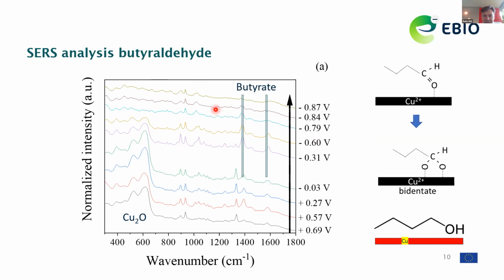And interestingly, when we start from butyraldehyde, we see a couple of bands appearing at intermediate potentials, which we can assign to the adsorption of the butyraldehyde in the form of an oxidized butyrate structure that you see depicted over here. So it's a kind of acidic C double bond O that is actually bound to the surface, and the double bond is divided over the two oxygens, and in that way it nicely bounds to the surface. And then if we remove the oxygen from the surface of the copper, we simultaneously reduce this butyrate structure, and then we start to see the product, which is in this case butyl alcohol. And then you see indeed these features disappear when we reach the potentials at which we perform the reaction of the butyraldehyde to form the butanol.